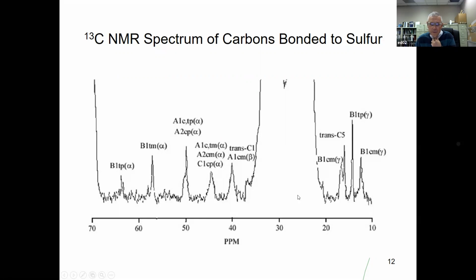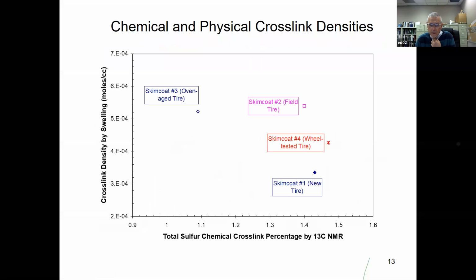So what we decided to do was integrate all these small peaks and determine the total percentage of carbons that are bonded to a sulfur. That data is plotted here. This is the percentage of carbons that are bonded to a sulfur atom. The new tire is 1.4%, and then the wheel tested tire, the field tire, the oven aged tire, and this is crosslink density.